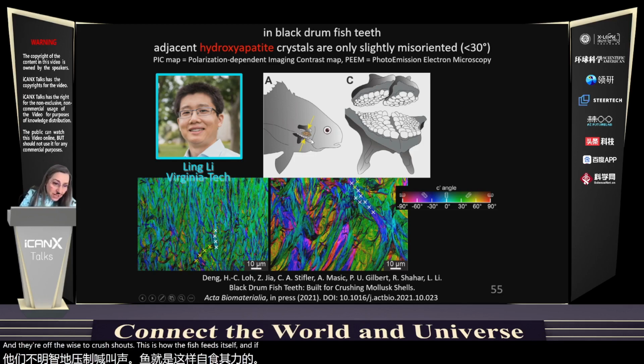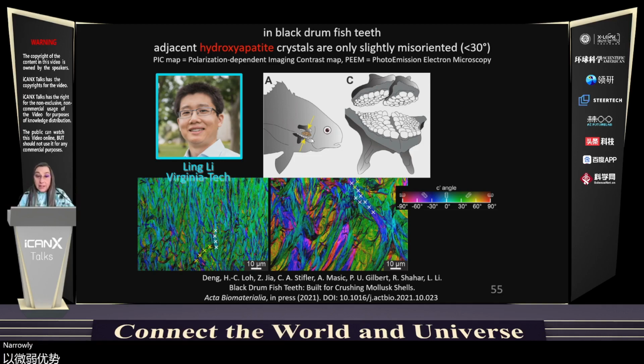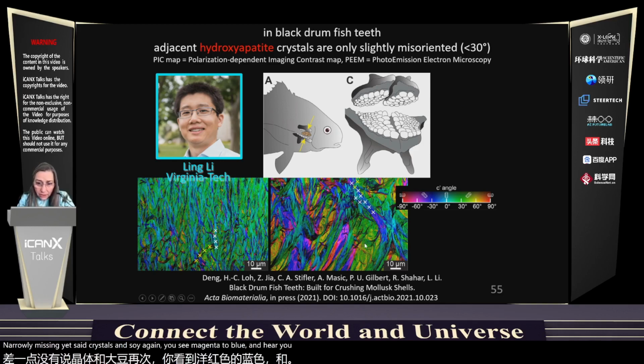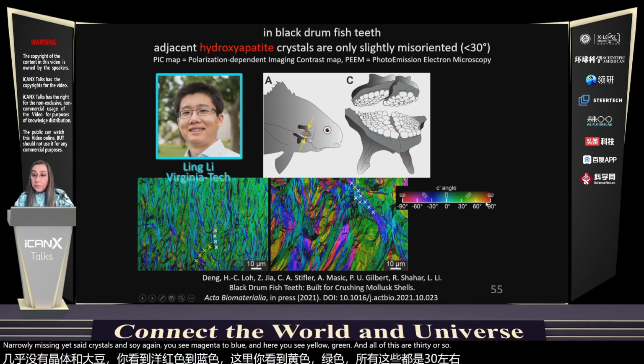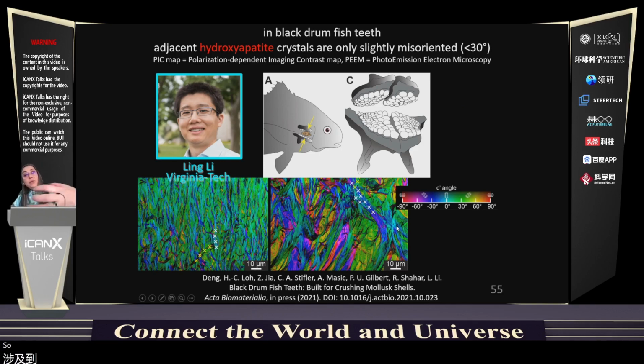And if we look at the structure with PIC mapping, we can see that adjacent crystals have narrowly misoriented crystals. And so again, you see magenta to blue, and here you see yellow to green, and all of this are 30 or so degree angles. So this seems to verify what we found in the carbonates, and then in hydroxyapatite.